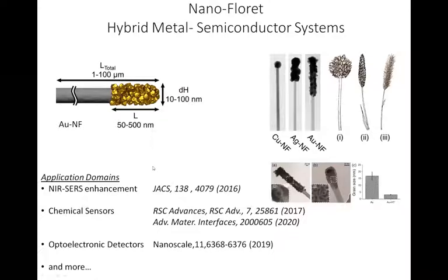So over the years after we published this synthesis in the JACS paper, we demonstrated chemical sensors and optoelectronic detectors, and now we work on a new type of detectors and devices, really. And we think this is a very interesting system because it combines all of these length scales where the nanowire can be quite long in the range of 1 to 100 or so microns, which is macroscopic. The diameter is in the 10 to 100 nanometer, and the length of the tip is from the tens to the hundreds. And then again, we can fine-tune the cluster size, and this gives a lot of opportunities to tune physical and chemical phenomena across scales and utilize it.